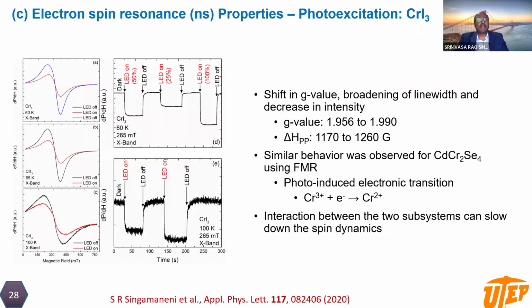To dig deeper, we conducted electron spin resonance measurements by shining light on it. Here we took an LED. We took spectra when the LED is off, when the LED is on, and then recorded the signal when the LED is off again, as a function of temperature from 60 Kelvin to 100 Kelvin. And we measured how the signal intensity changes as a function of time. We analyzed the data and extracted some numbers. These numbers are important here. One is the g value, which shows how strong the spin-orbit coupling is, and we saw that number increased. That means the spin-orbit coupling of this compound increased upon photoexcitation. Another number is delta H_pp, the peak-to-peak line width of the signal. This line width also increased. That signifies that we are changing the interactions at the local chromium 3+.